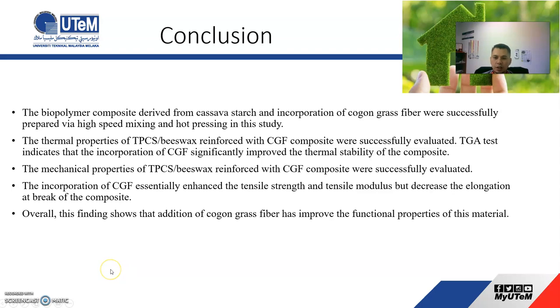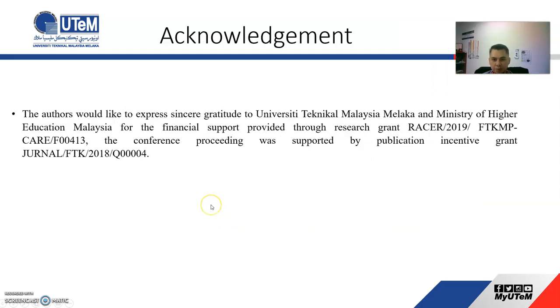So as the conclusion, the biopolymer composites derived from cassava starch, beeswax, and also cogon grass fiber were successfully prepared by using high-speed mixing and hot press. The thermal properties were evaluated and indicate that it improved the thermal stability of the composites. And same goes for the mechanical properties. The addition of CGF essentially enhanced the tensile strength and tensile modulus, but decreased the elongation. So overall, the findings show that the addition of cogon grass fiber has improved the functional properties of these materials.